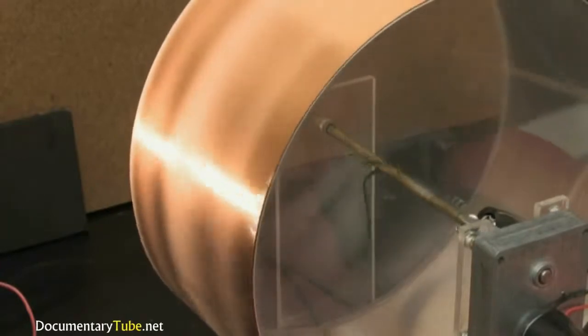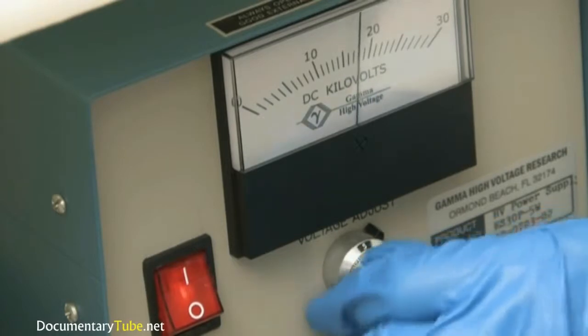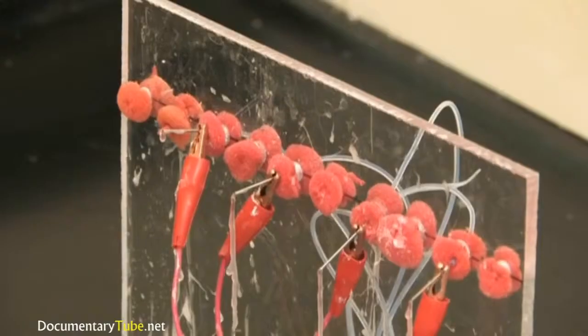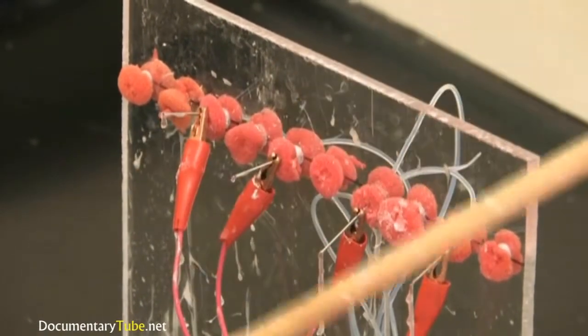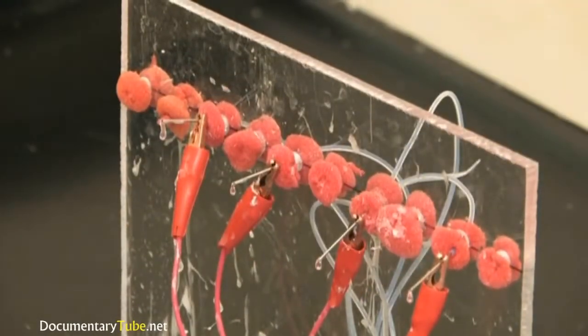We form a droplet of the polymer solution. We apply high voltage to that droplet, something on the order of 15,000 volts. A very fine jet of polymer will erupt from the surface of that droplet and is collected over on an electrical ground some distance away.